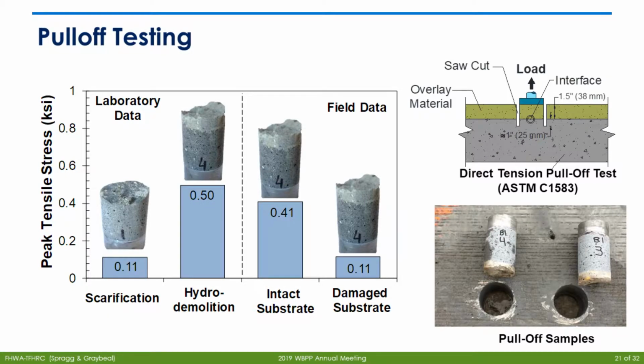Right, so here's what the data looks like. Looking at field data and laboratory data, you can see that the scarification was a little bit lower than the hydrodemolition, and then some of the other ones that we looked at as well. The reason for that has to do with how well the overlay is consolidated, and also damage that might happen to the aggregates during the scarification or the hydromilling process. We'll take a look at that in the next couple slides.